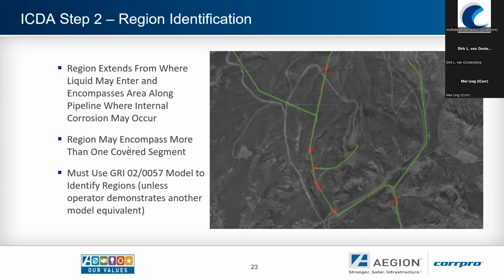And so when we start to look at the ICDA, one of the big issues here is that we may have a region, but it may actually cover more sections as far as the high consequence or moderate consequence. And this is where the Gas Research Institute had some additional guidelines that are useful when it comes to actually modeling out these regions. And if the operator chooses not to follow that specific requirement, they have to then determine and demonstrate the applicability of whatever other model it is that they wish to use.